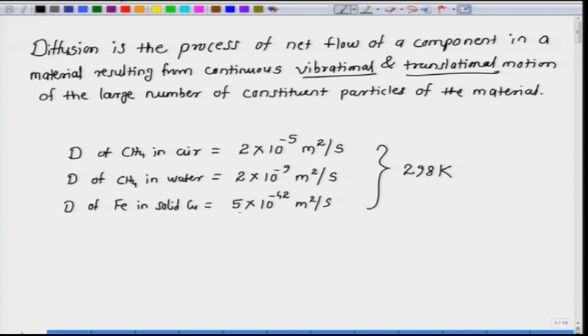You will notice the diffusivity of iron in solid copper is ridiculously low, much lower compared to the general diffusivities in air or water. Even if you consider 900 degree centigrade, which is very close to the melting point of copper, the diffusivity of iron in copper comes out to be around 10 to the power minus 14 meter square per second. So, even at 900 degree centigrade, diffusivity in solid copper is around 5 orders of magnitude slower than the diffusivity of methane in water, and 9 orders of magnitude slower than the diffusivity of methane in air. So, if we talk in terms of the diffusion distances, which is easier to see.